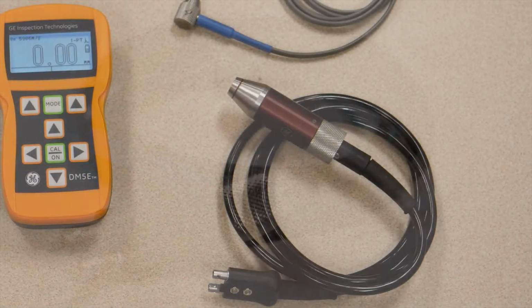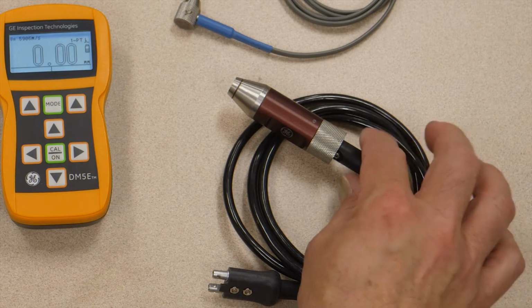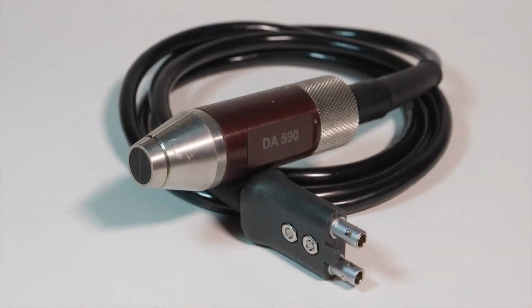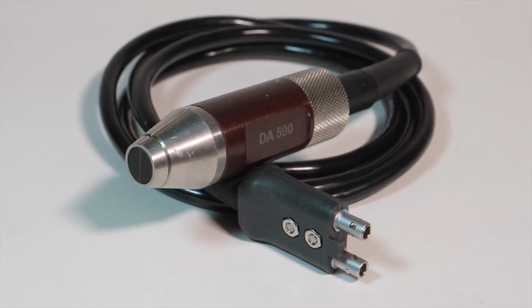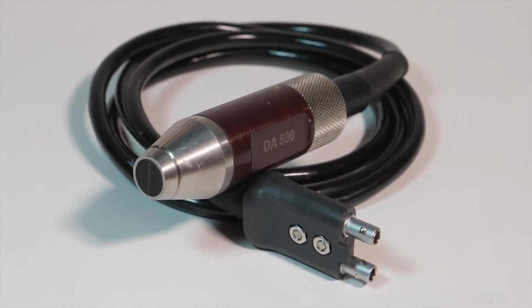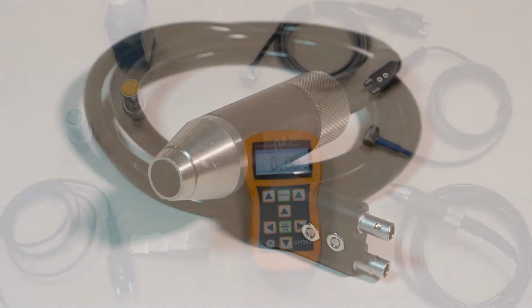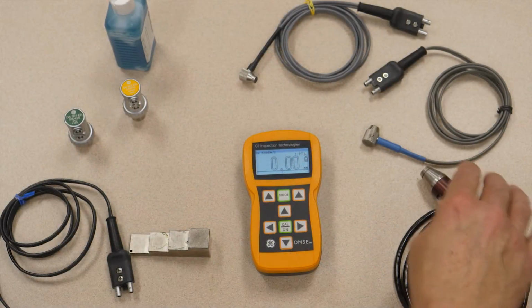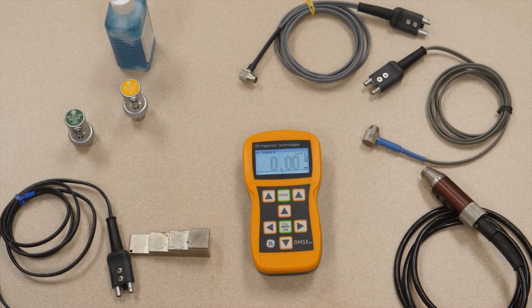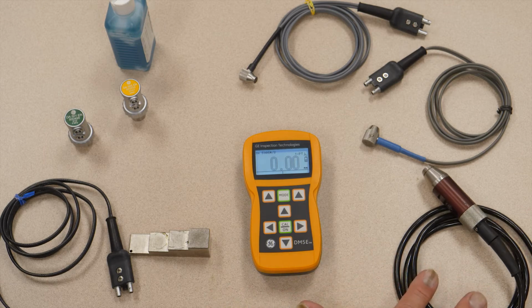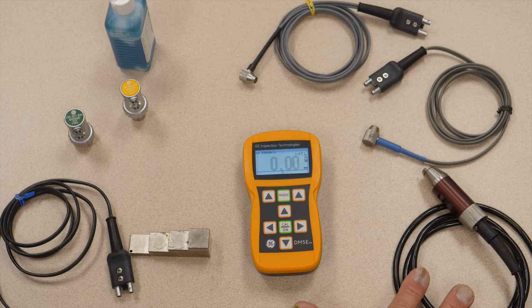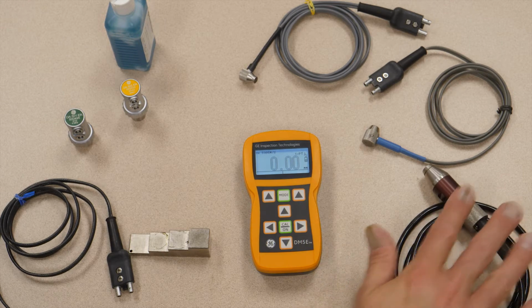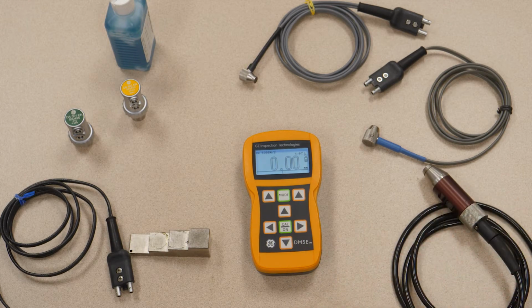And we also offer the DA590, which is a high temperature probe. You can measure on materials up to 400 degrees Fahrenheit with this probe. It's built to take the high temperatures. Now the DM5E, unlike the DMS Go, our more advanced gauge, doesn't offer temperature compensation for the measurement. So you're still getting the raw thickness measurement, but the DA590 probe is available to work at higher temperatures.